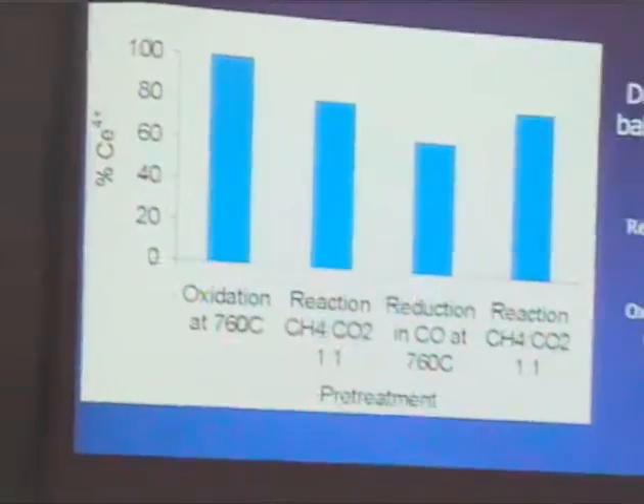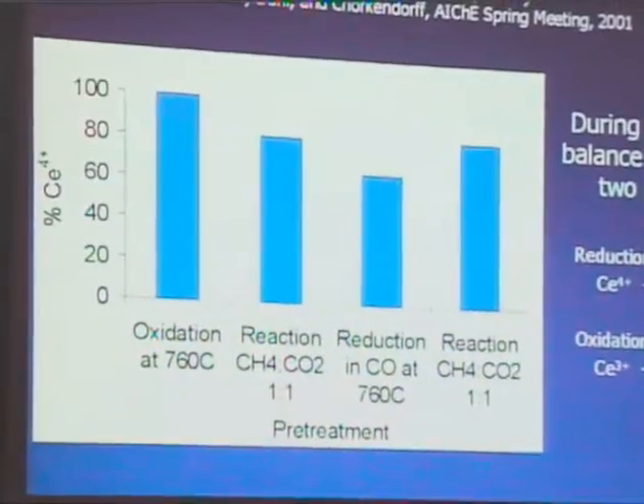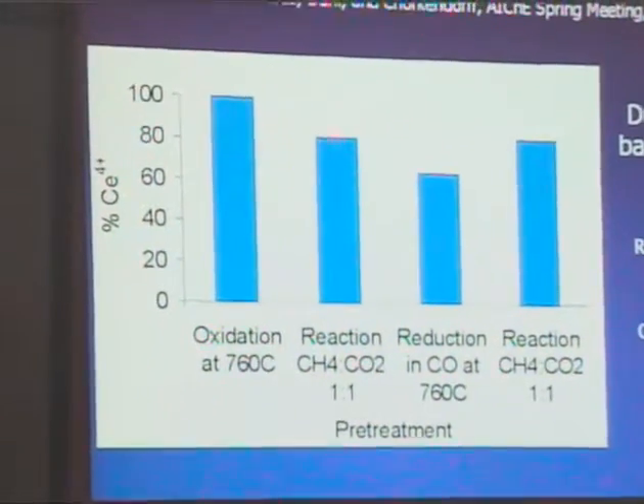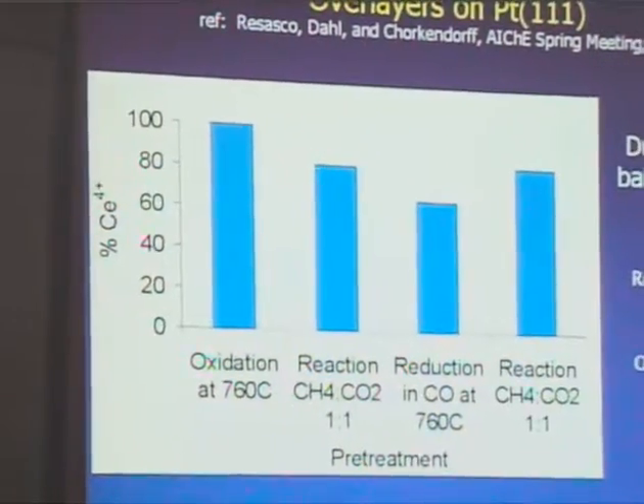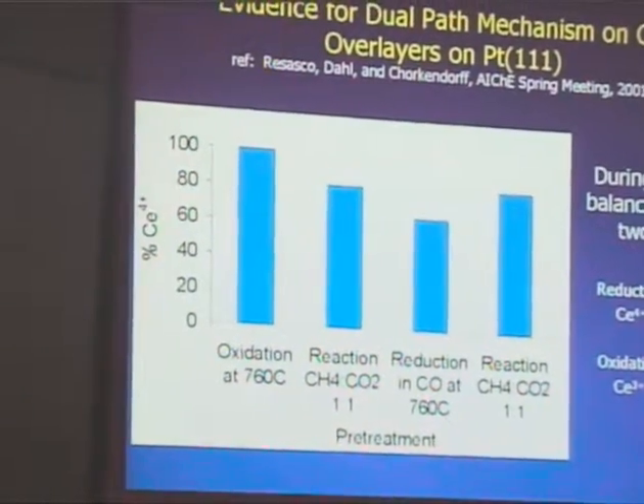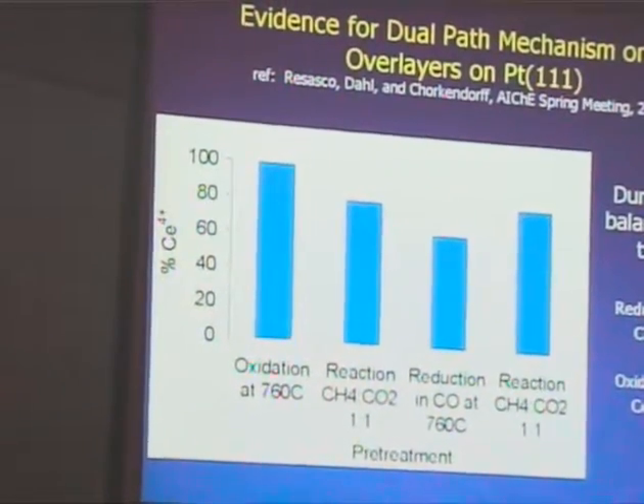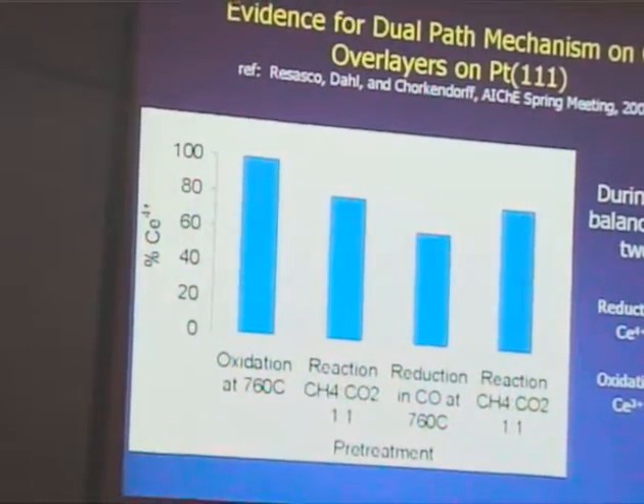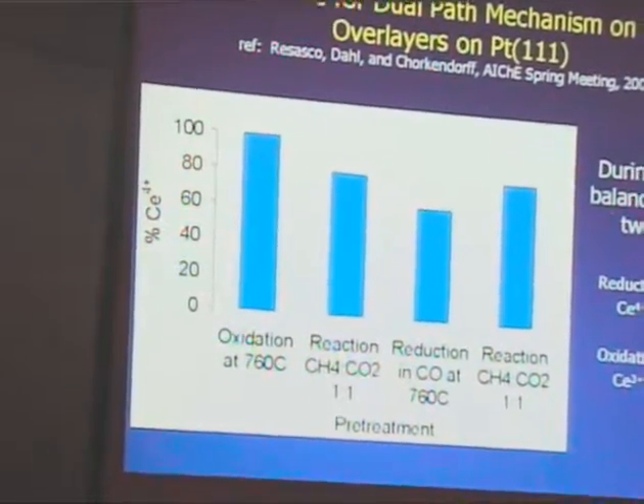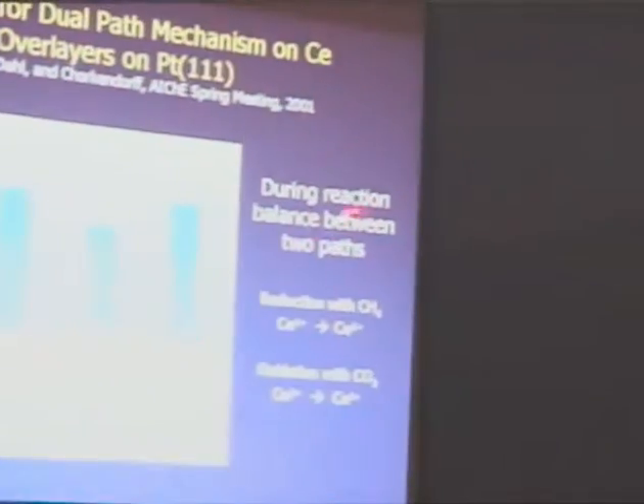If you do the reaction of methane and CO2 at a 1-to-1 ratio, you now see that you have about 80% of the ceria in the 4 plus state. Right? That would come from the fact that when you have the dry reforming reaction, you have the balance between these two paths. This is what I talked about before. Reduction with methane would take it from ceria 4 plus to ceria 3 plus, and oxidation with CO2 would take it from the 3 plus to the 4 plus state.